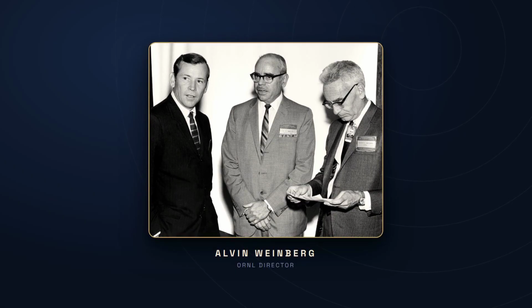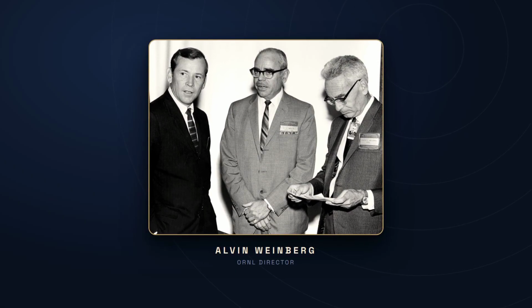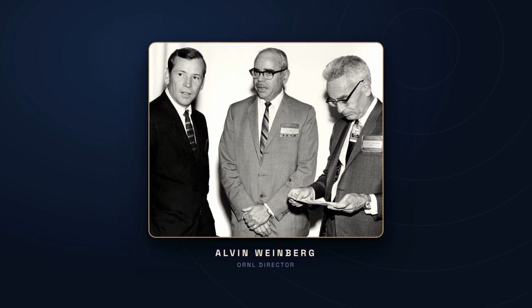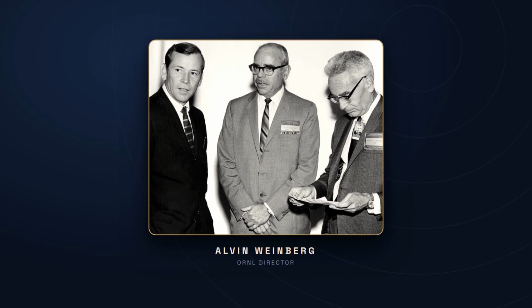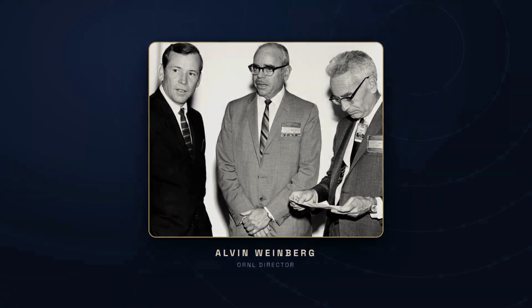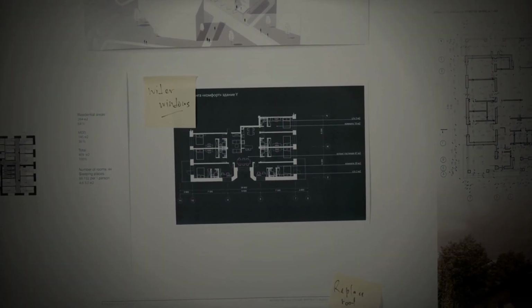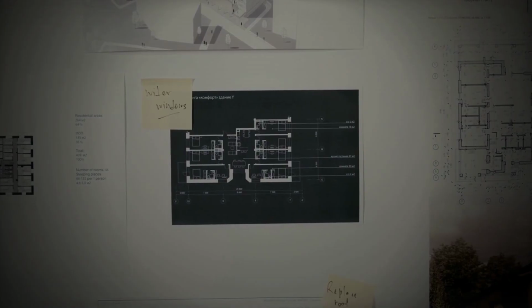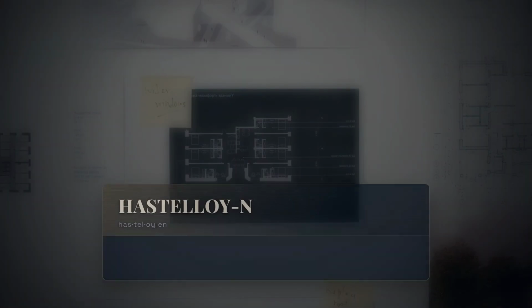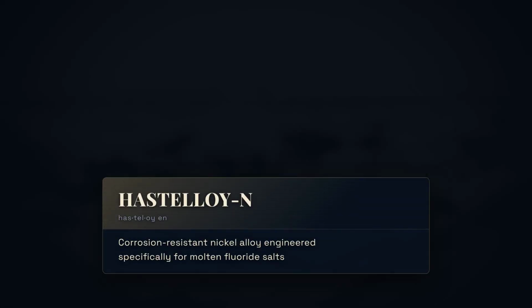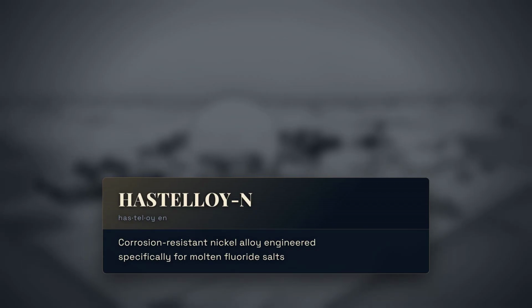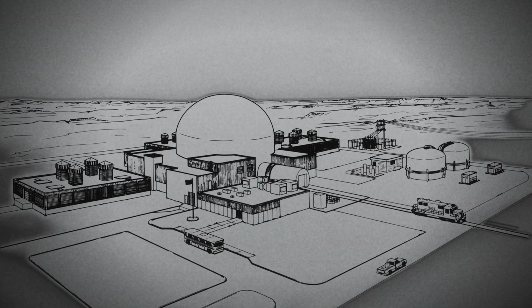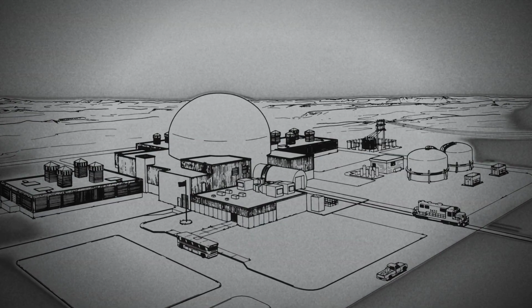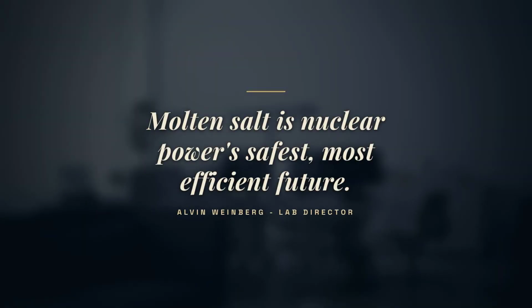For 4 years, the reactor ran almost continuously. Engineers logged more than 13,000 hours of operation, cycling through uranium-235 fuel, then uranium-233 bred from thorium, proving that a liquid fuel design could sustain fission reliably, refuel without shutdown, and survive the corrosive chemistry of molten fluoride salts using a nickel alloy called Hastelloy-N, developed specifically for this program. Alvin Weinberg, the laboratory's director, believed molten salt technology represented nuclear power's safest, most efficient future.